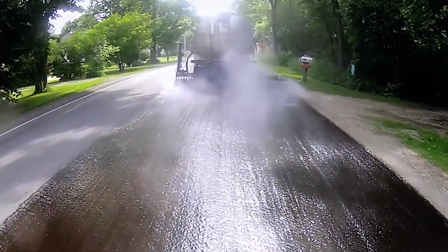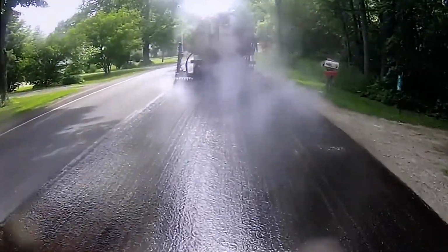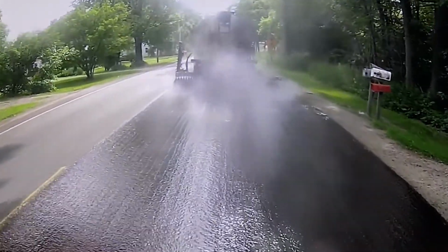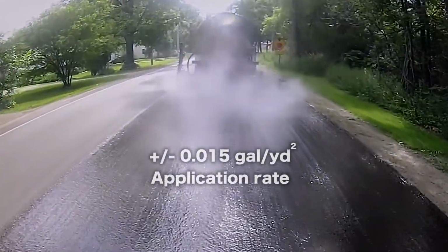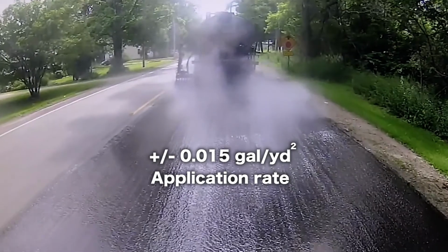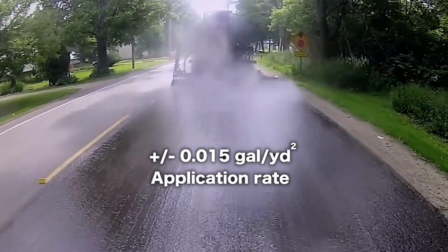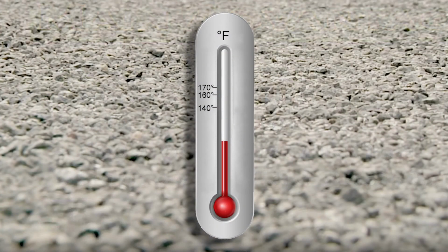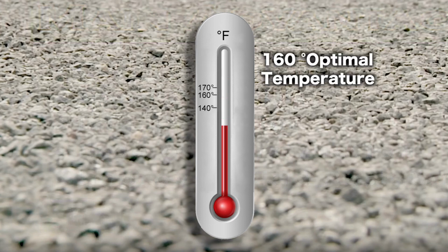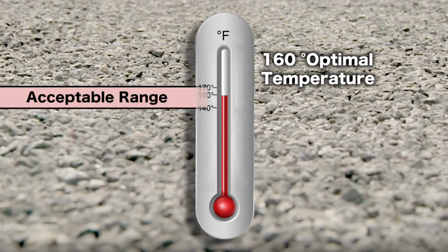The Etnyre distributor is capable of maintaining the specified application rate within plus or minus 15 thousandths gallon per square yard for each load. Optimal temperature of the emulsified asphalt at the time of application is 160 degrees Fahrenheit with an acceptable range of 140 degrees to 170 degrees Fahrenheit.